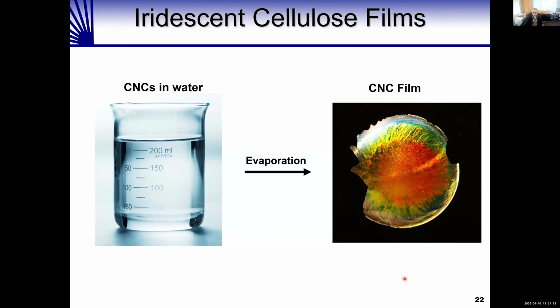They have an amazing property. On the left is a beaker of dilute cellulose nanocrystals in water, and as you might expect, they're colorless. But if you let the water evaporate from this beaker and concentrate those cellulose nanocrystals, you get a colored iridescent film, as shown on the right. So there is no dye or pigment being added, but we're getting color from a material that is colorless.